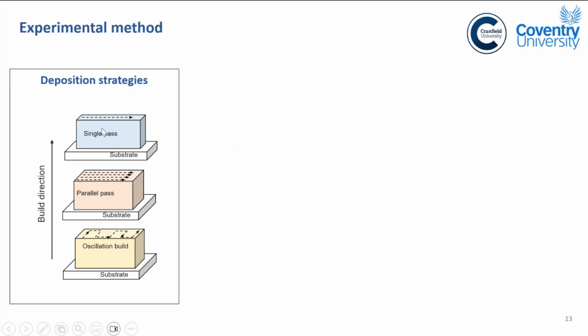If the samples are thin structures like aerospace, they just use single pass weld. If the samples are thicker, they try the parallel pass, four times of welding for each layer, or oscillation. I think the conclusion currently, after 15 years, is they would prefer oscillation build over the single pass.